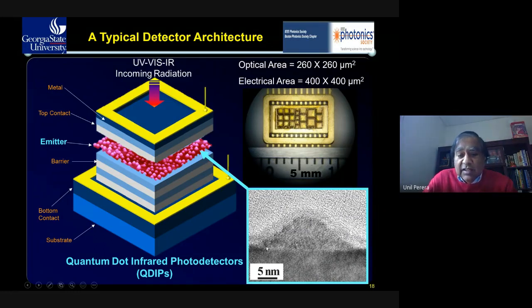So this is the size scale. You can see this is like 20 nanometers here. And this is a device which we have used with structures which have different sizes, 260 by 260 micron optical area. Electrical area is a little larger, 400. So in one chip carrier, we have several devices because we want to check for the leakage, edge leakages.